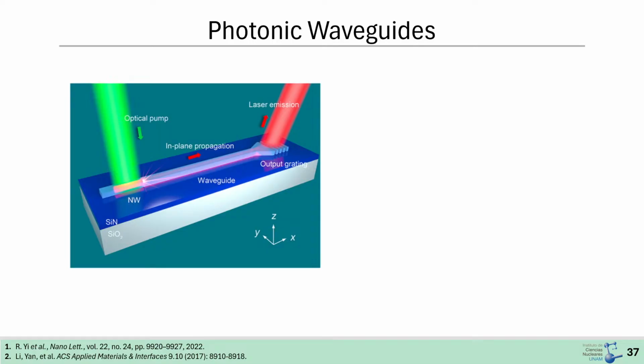I'm also interested in studying photonic waveguides, and one of them is where I have a semiconducting material that can be optically pumped, embedded in polymer. Polymer we can basically mold into any shape. And the polymer has a dual function. It protects the semiconducting material from the ambient environment, and it can basically guide the light.